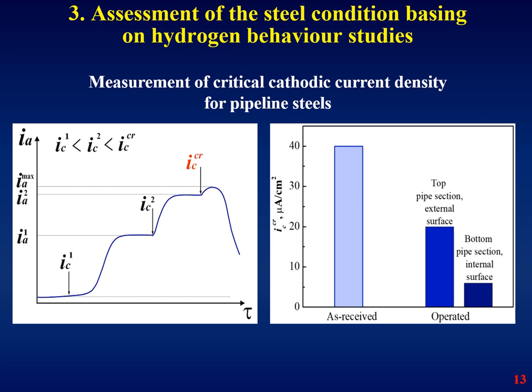The electrochemical method of hydrogen permeation was used for estimation of the metal's susceptibility to hydrogen-induced cracking. For this purpose, the cathodic current density applied to the ingress surface of the metal membrane was increased step by step. Each time this led to an increment of anodic current density in the egress cell. The regularity continued until damaging occurred under the combined action of hydrogen and residual stresses induced by intensive hydrogen charging. Then a sharp decline appeared on the ionization curve on the egress side of the membrane, indicating the trapping of hydrogen by newly formed defects — that is, the development of hydrogen-induced damaging. The cathodic current density corresponding to defect occurrence is considered as critical. Metal in the initial state, in comparison with exploited steel, is characterized by a higher level of critical cathodic current, meaning more resistance to hydrogen cracking.